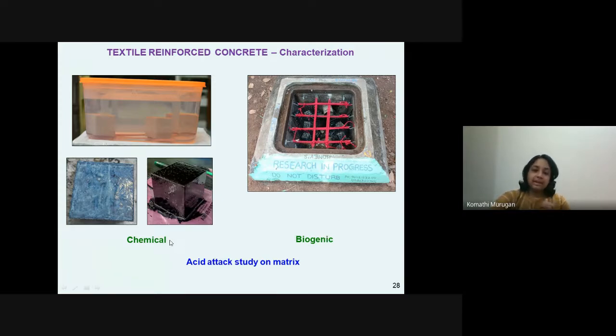So in the chemical attack study, what we essentially do is use coated and uncoated specimens. The specimens which are shown in the tub here immersed are the uncoated specimens, that is the direct matrix cubes, which are immersed in a certain concentration of sulfuric acid solution. What we actually check is also what happens. We definitely know that the matrix gets deteriorated at a point of time.